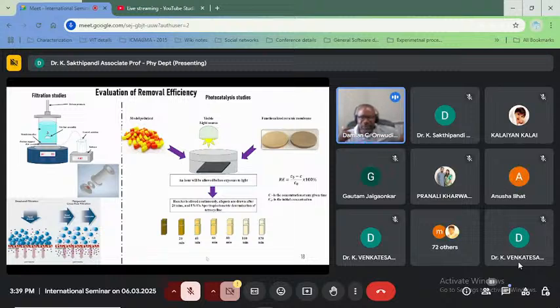We tested it on our ceramic membrane, whereby we took aliquots, introduced it into water, and irradiated it with visible light. Why visible light? Because we know that a large amount of solar energy is in the visible range, while less than 2% is in the ultraviolet region. So we focused on the effectiveness of this ceramic membrane in the visible range of the solar spectrum. After irradiating it, we took aliquots at time intervals and established the degradation pattern, which we are going to see in the next slide.